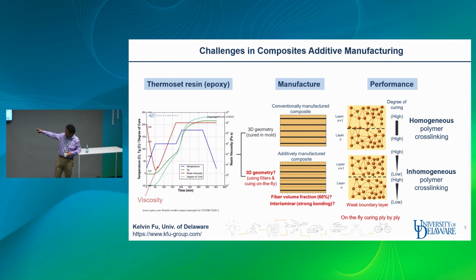And also the curing time. If you look at the curing time, it's around 400 minutes, a few hours. So normally we cannot wait several hours to print a short period of composite under the printer head. And most importantly, the other challenge is the interface.